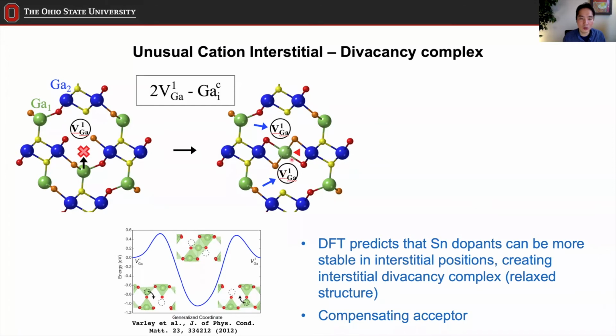Okay, so that atom jumped into the interstitial site, meaning there now you have an interstitial atom defect itself. So now that's what we're seeing, right? Those are all interstitial atoms. So now we have the atom jumping into this site, which creates another vacancy. So you end up having two vacancies and one interstitial atom, and they are all paired, right? So they make their own complex. It's a new type of complex that appears, that was predicted by the theory. So we can call this complex an interstitial-divacancy complex, because it has one interstitial and two vacancies. Okay, so that's what the theory has predicted before.